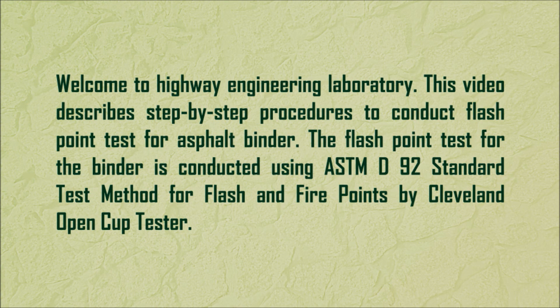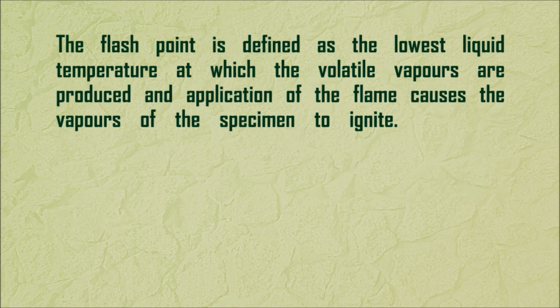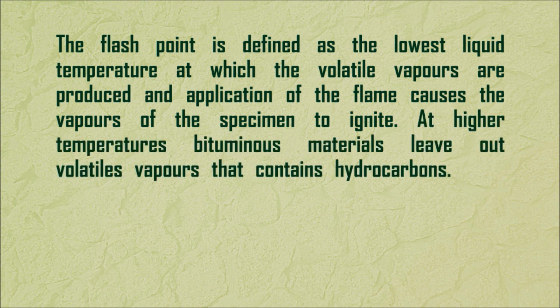The flashpoint test for the binder is conducted using ASTM D92, the standard test method for flash and fire points by Cleveland Open Cup Tester. The flashpoint is defined as the lowest liquid temperature at which volatile vapors are produced and application of the flame causes the vapors of the specimen to ignite.